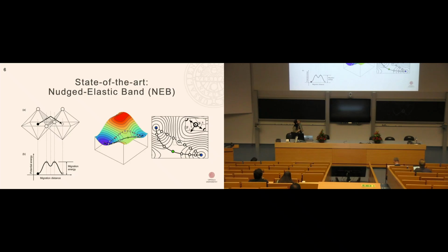And this approach often works very well when you're looking at individual systems or within structural groups, where you know already beforehand the topology of the potential energy landscape. Because with the nudged elastic band method, you need to know where the energy minima are and the approximate transition path between them. So this really limits the applicability for extending towards materials where the transition state landscape is not already known beforehand.